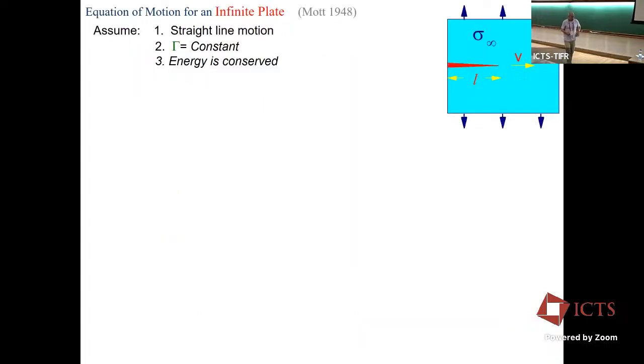So right now I'm gonna hand wave and derive actually a quite correct equation of motion. And to do that, I'm gonna follow the argument that was originally put forward by Neville Mott to explain the broken ships. Okay, so we're going back in history. And so here's our system. We're applying at infinity, it's a large infinite sized plate. Ships were big in those days. So we're applying some stress sigma infinity at the boundaries, again, under pure tension. We're assuming that the instantaneous length of the crack is L and its instantaneous velocity is V.